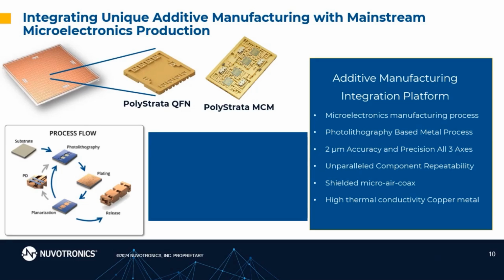process. The XY dimensions are lithographically defined, so plus or minus 2 micron precision. The Z height is planarized to the same level of precision. And the surface finishes on the sidewalls, the bottom surface, the top surface of each layer are all better than 100 nanometers roughness. Here I've got a nice animation showing how one of our package products is built using this process.